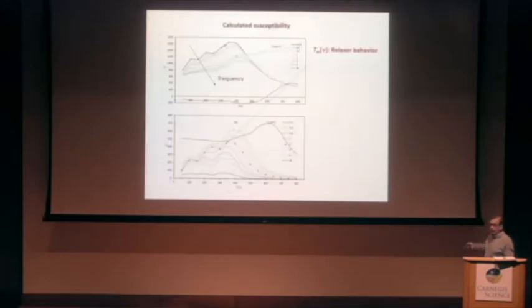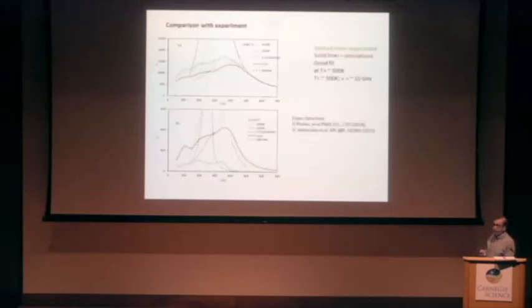Thus, we calculated the relaxation and oscillation parameters at every temperature, and then we can calculate the temperature dependence of the susceptibility. It's quite a familiar picture. The maximum of the real part of susceptibility increases with frequency, as it should be in relaxers. And this is the quantitative figure. Now let's compare this data with experiment.